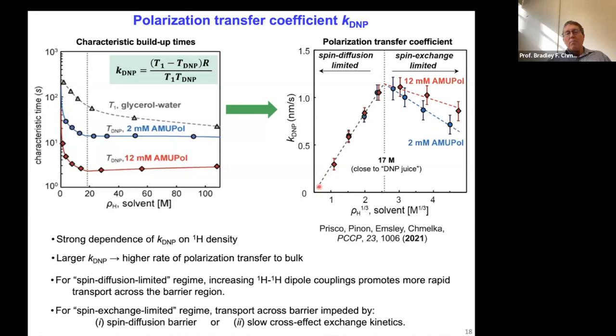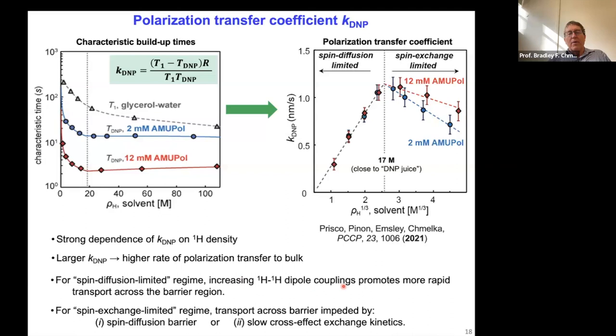So you don't want a fully deuterated solvent — you want protons. The more protons you add, the more polarization you get. But one might think: why not use a fully protonated solvent? The answer is because as you continue adding protons, you have dipole-dipole couplings that can have relaxation effects, and the rate of polarization transfer coefficient eventually diminishes, depending on the bi-radical concentration. What we have is a volcano plot with two regimes: one that is spin-diffusion limited — you're limited by how fast you can take polarization away from the paramagnetic center — and one that is spin-exchange limited.